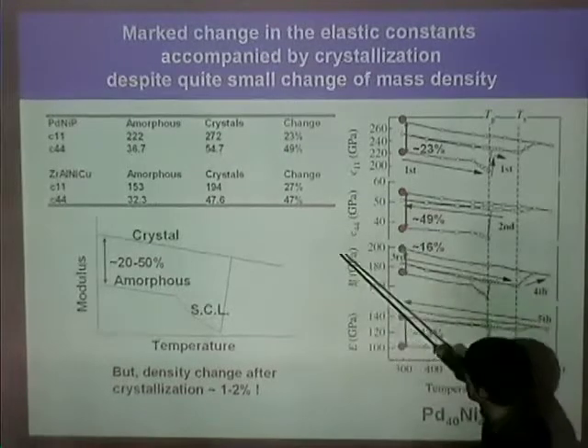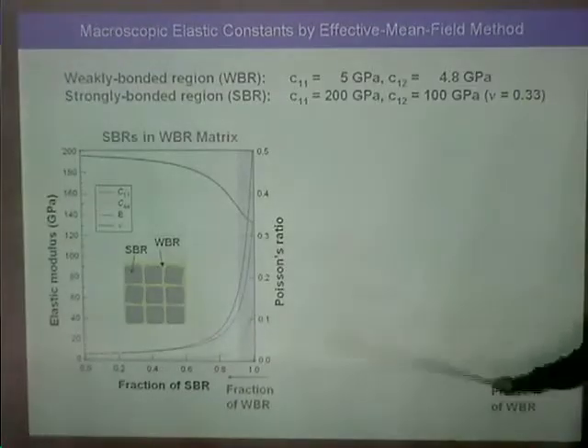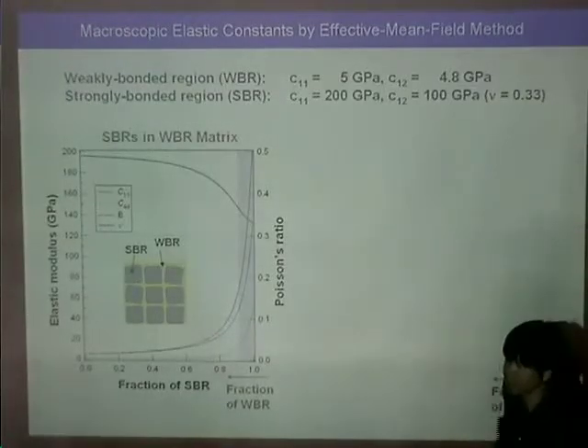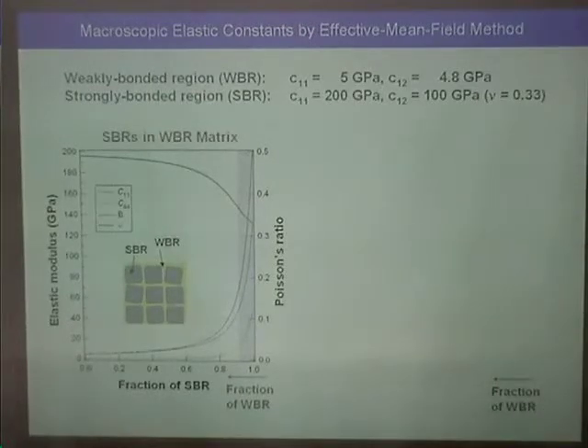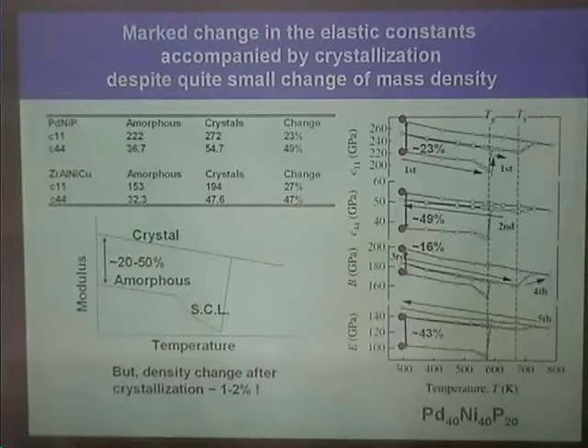So in order to explain this phenomenon... Can I interrupt for a second? That's quite general. My impression, though I haven't read the literature on this very much, was that the elastic properties of the amorphous glasses were typically about 10% less than. No, 25%. It is 25 to 50%. Yes, 50 for the shear modulus. I mean, he divided the change by amorphous. If you call crystal 100%, it's 100%. Yeah, that's right. Anyway, 25 is about right.